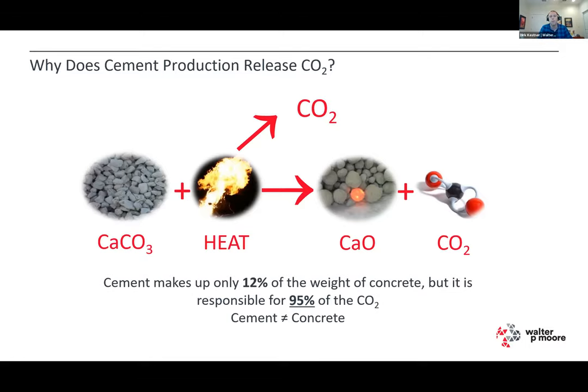So when you're looking at mix designs, every pound of cement is about a pound of CO2. That's why cement is only 10 to 12% of the weight but represents the vast majority of the CO2 for the concrete. And it's important to note: cement and concrete are not the same thing. Concrete is what comes out of the back of the truck; cement is a component of it.